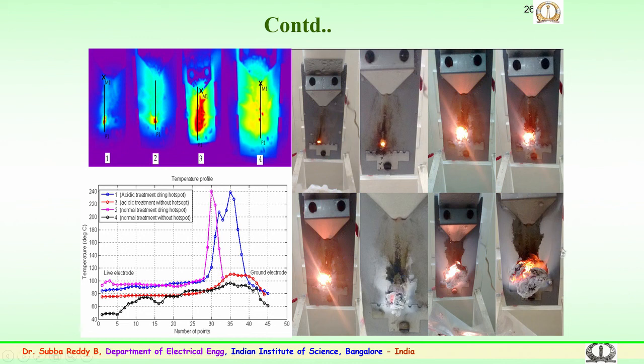Suitable arrangements both for AC and DC have been made, and the temperature has also been measured during the process. Here this gives the temperature profile, temperature versus the number of points, and we have given both for a normal case and acidic case, and you can see the variations at different locations also. Very important aspects: sometimes the electrodes are also damaged because of the experimentation, with pitting on the electrode. Not only the sample rupture, there is a hole on the surface of the rubber samples which happens during the process.